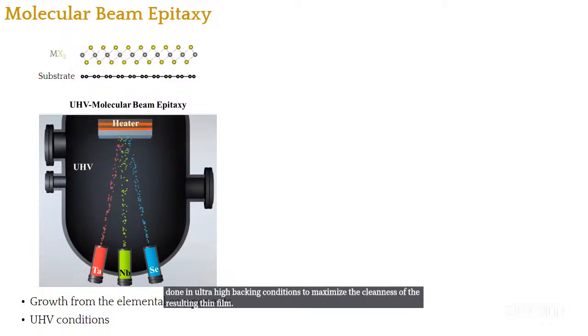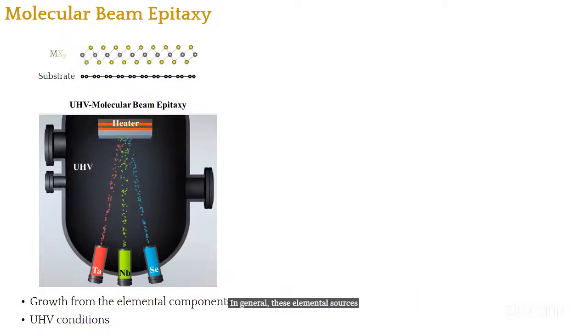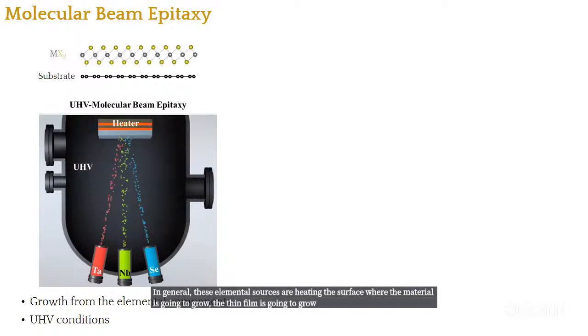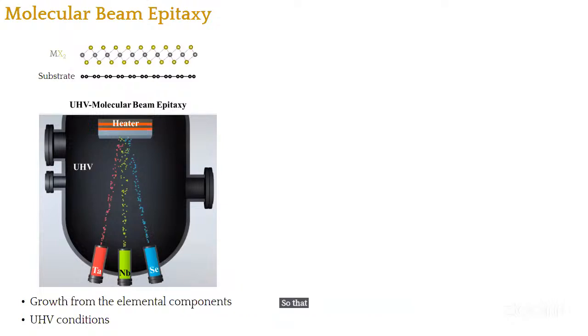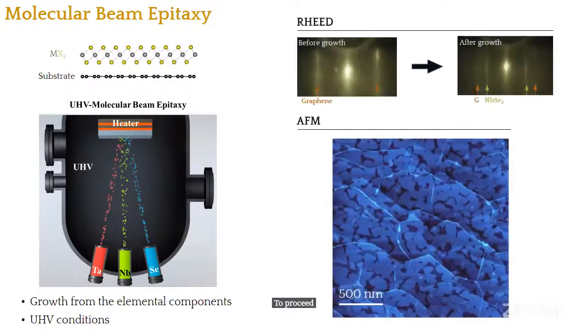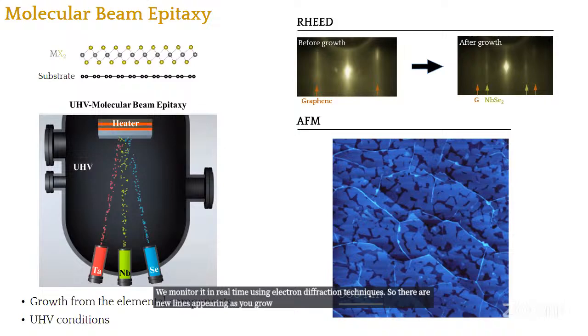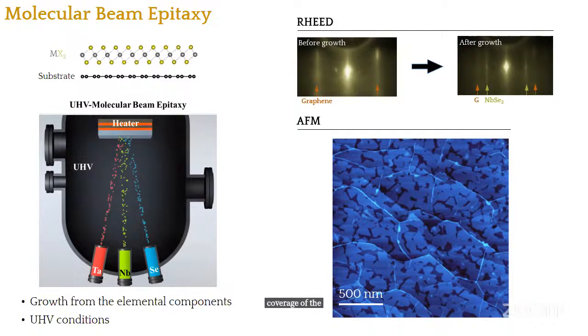In general, these elemental sources are directed at the surface where the thin film is going to grow, which is usually kept at high temperatures, so that the kinetics and the chemistry can take place. That's the way to proceed with these materials. In our case, we monitor the growth in real time using electron diffraction techniques. New lines appear as you grow the material that give you information about the coverage of the material or the number of layers, et cetera.